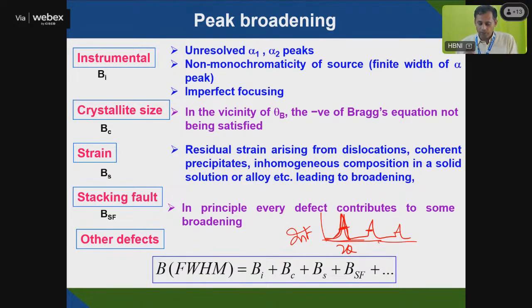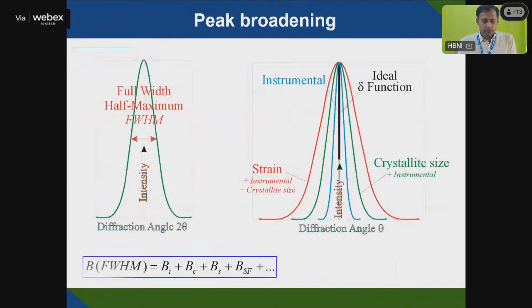If you see the perfect XRD pattern of a bulk material, what you will get is a delta function, this type of intensity versus 2 theta. You will get only a sharp line, no peak, in the case of a perfectly bulk material. But if you go to smaller and smaller sizes, like nanomaterial, instead of bulk, you get a broad type of pattern. You can see it here.